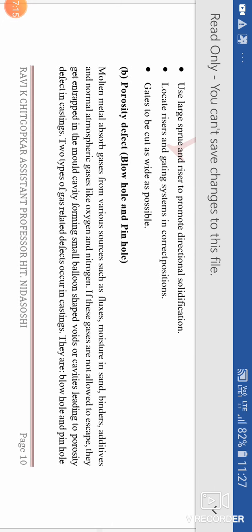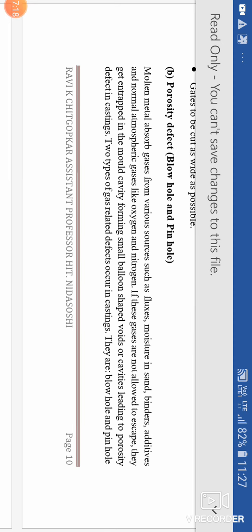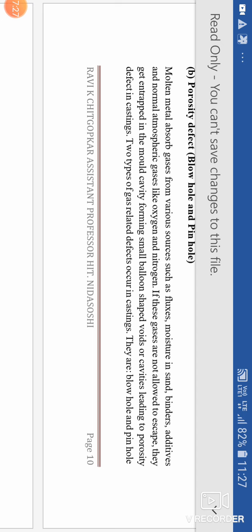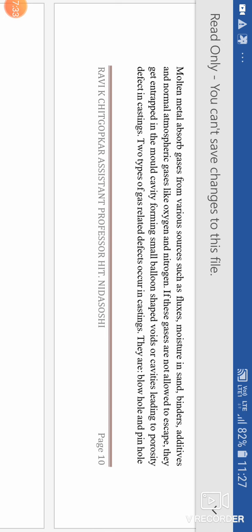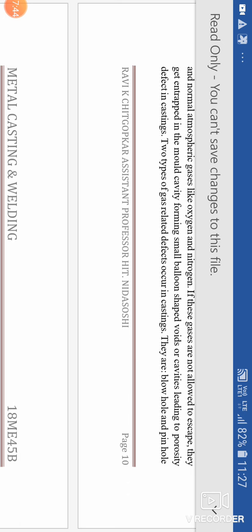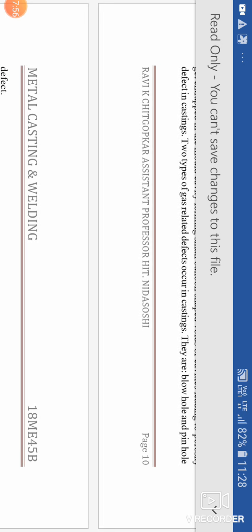B. Porosity defect, blowhole and pinhole. Molten metal absorbs gases from various sources such as fluxes, moisture in sand, binders, additives, and normal atmospheric gases like oxygen and nitrogen. If these gases are not allowed to escape, they get entrapped in the mold cavity, forming small balloon shaped voids or cavities leading to porosity defects in castings. Two types of gas related defects occur in castings, they are blowholes and pinholes.